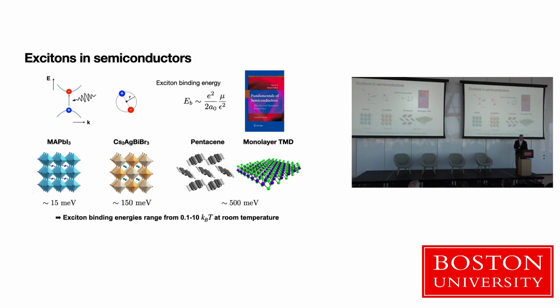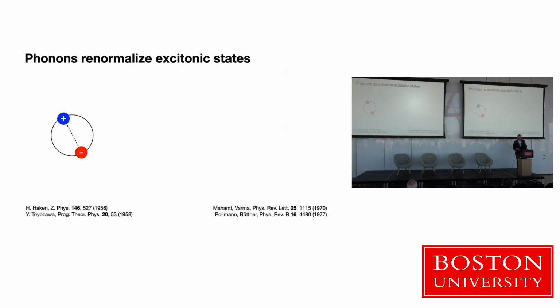And so it's critical to note that these binding energies straddle kT at room temperature. So kT at room temperature is 25 millielectron volts. And so you could imagine that neglecting any kind of lattice effects or temperature effects might not be a very good approximation. But that is actually the state of the art. So this is something we wanted to advance.